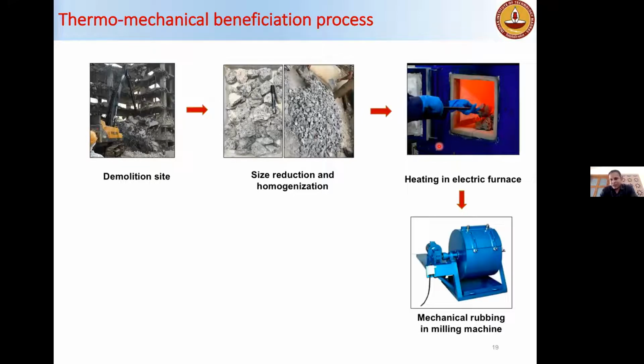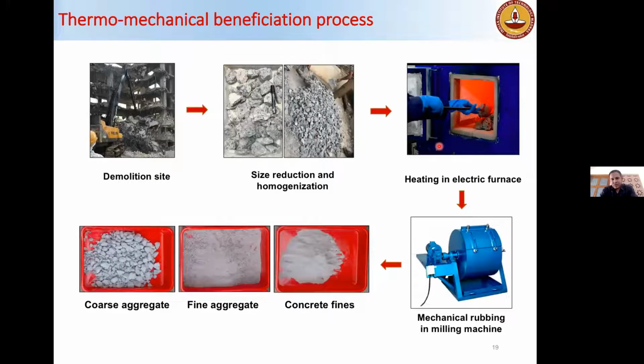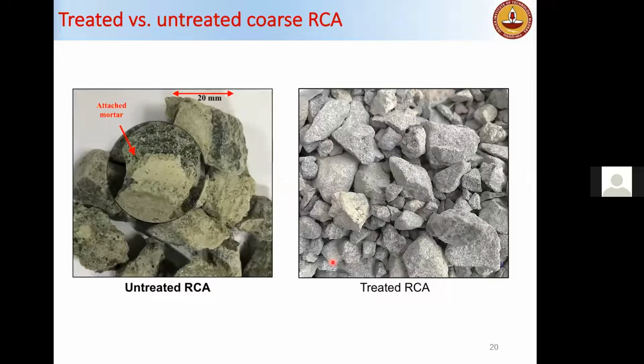And then after the cooling and the mechanical milling, you got these three products: coarse aggregate, fine aggregate, and the concrete fines. The coarse aggregates are sized from 20 mm to 4.75 mm, and your fine aggregate is 4.75 mm to 300 microns. And this is the concrete fines, or the powder, which is less than 300 microns. You can see after the treatment, the aggregate looks like this. You can see that almost all the attached mortar is removed. Let me just show you the aggregate piece.